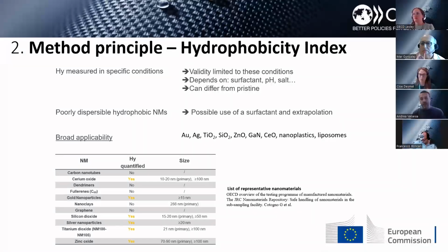During our work this year, within the development of the test guideline but also with the many other projects we have in this framework, we demonstrated that the technique has broad applicability to different materials. We measured gold, silver nanoparticles, titania, silica, zinc oxide, gallium nitride, ceria, but also the hydrophobicity of novel pollutants like nanoplastics or nanomedicines like liposomes or other liposome-based nanomaterials.